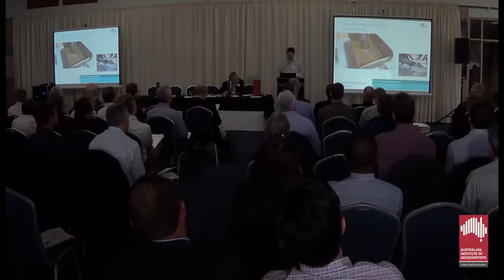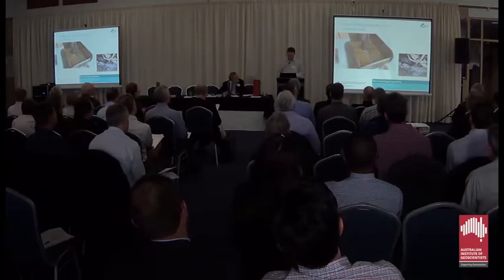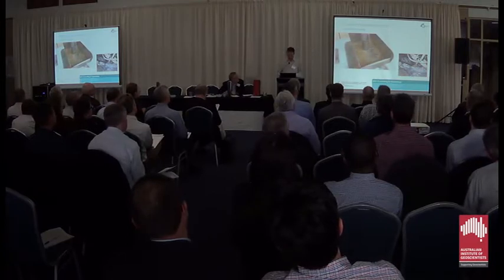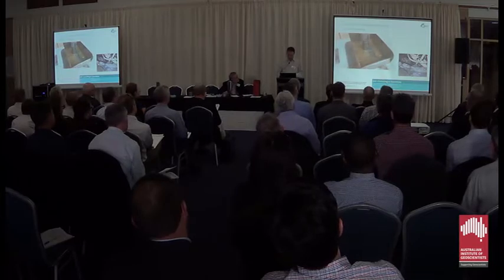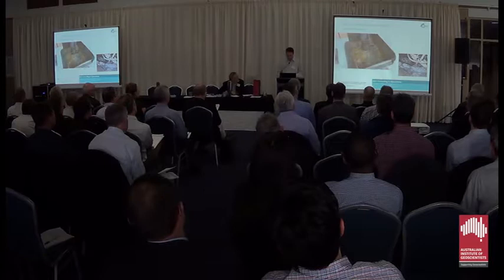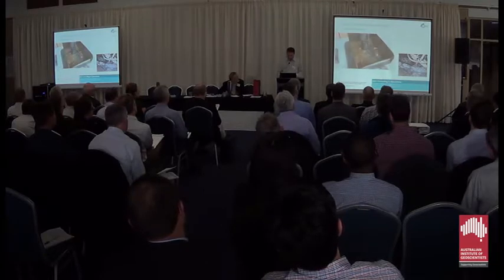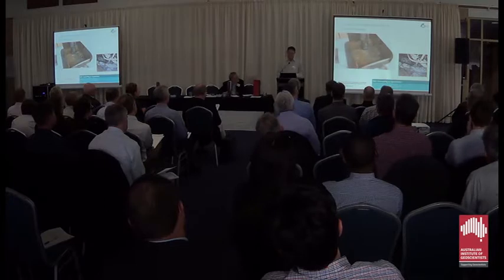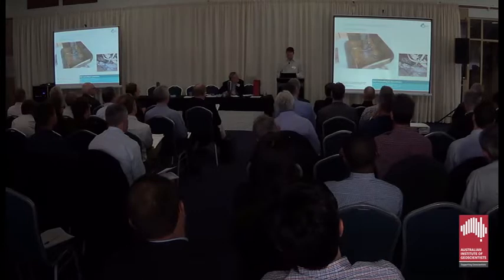As the collector mixes through the slurry, which is known as conditioning, you'll start to see the graphite concentrate on the surface of the slurry. Most of you will at some stage have mixed a fuel oil with water and seen the fuel oil float to the top of the water as a slick, which is essentially what's happening here. Some of you may have seen firsthand, or in various company releases, a form of graphite flotation during the drilling process, where graphite is flowing out of the rig with contact from the drilling oil or water with the liberated graphite flake.